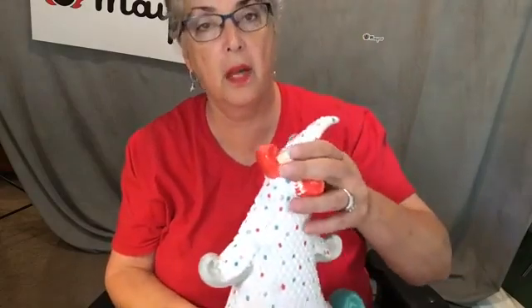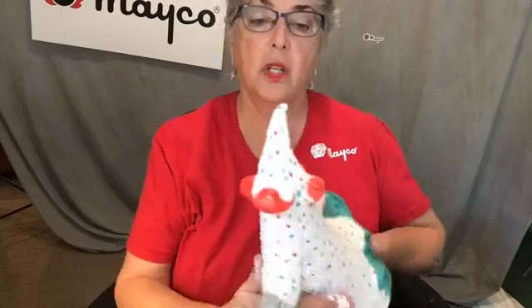So if you put it on about the thickness that I showed you, where you're really kind of filling in the little holes and not really piling it on, you'll get a good coverage. Right here, like I showed you guys earlier, look how it cracked. I piled that bad boy on and just forced it a little bit too much.